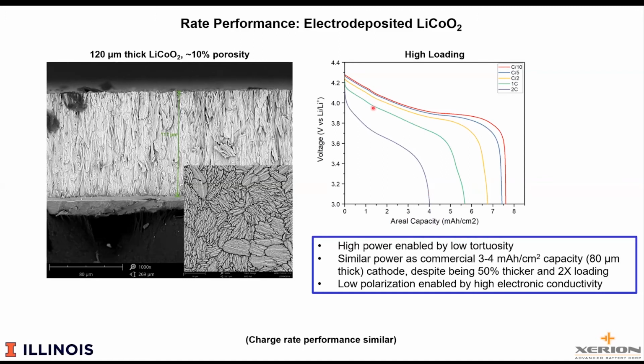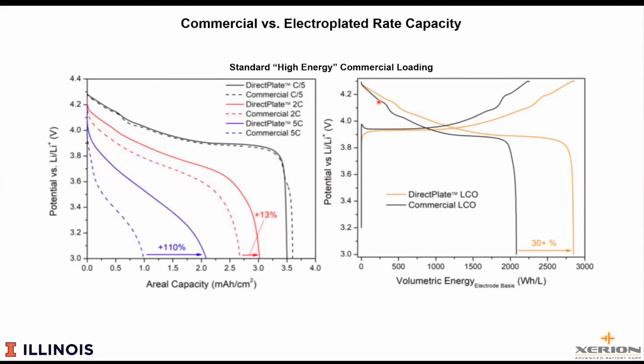And this difference here is the electronic polarization. And so the electronic polarization is near zero. And that compares again with commercial systems where the electronic polarization is also significant. But this is actually, I'd say, more of an apples to apples comparison. What we're looking at here is a commercial electrode that has 3.5 milliamp hour per square centimeter and a plated electrode of 3.5. This is C/5, so that's a 5-hour discharge.